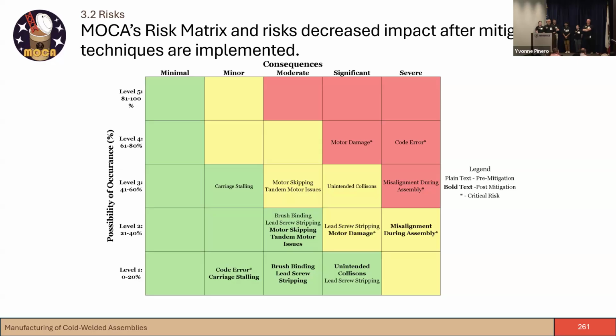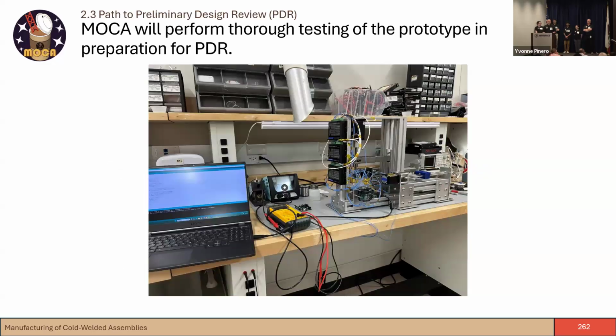As you can see, we did some mitigation to these risks. For motor damage, you can see that it has gone out of the red and into the yellow, which is still, it still could occur, but it's a little lower. The mitigation we did for that was when we would degrease, or replace the grease in the motor, we wouldn't completely get rid of all of the grease. We would get rid of a small amount. So when we put it back in, nothing significantly changed. And we would also pre-bake it, so there is no damage to the motor. Next slide, please.